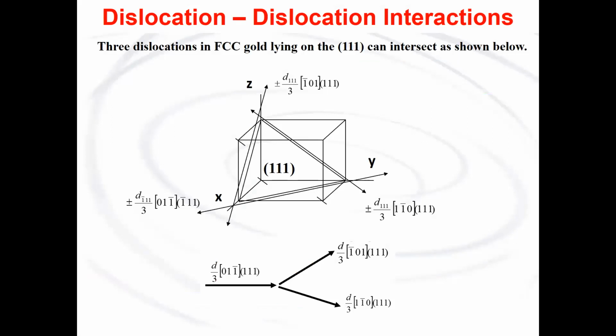So here I start with a 111 plane within a face-centered cubic. My specimen is gold, and the deformation directions are the 110 directions. And you can see here we have the possibility of 6 110 deformation directions on the 111 planes. So you can have a dislocation with Burgers vector d/3, where d is the interatomic spacing of the 111 plane, in the [0 1 -1] direction, lying on the 111 plane. It can split into d/3 [-1 0 1], as well as d/3 [1 -1 0]. If we add these 2 vectors here, they come out to the same vector. So everything's consistent.